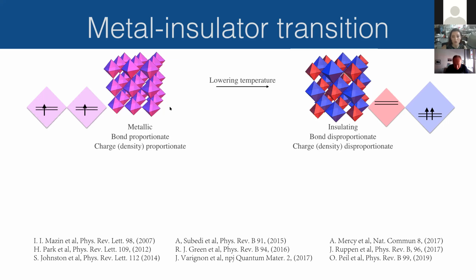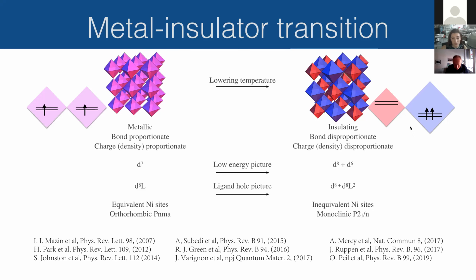Then, when you lower the temperature, you go through this metal insulator transition, and you get to the insulating state, which is a bit more interesting. So now you have alternating small and large octahedra, and going along with this, you have alternating empty EG orbitals, and now an EG orbital that has 2 electrons in a high spin configuration. So this is called bond disproportionate, because now there's 2 different sizes of nickel-oxygen bonds, depending on the octahedron you're in, and it's charge disproportionate. And you can describe this, like the low energy picture, which I have sketched here, or in the ligand hole picture, which is much more difficult to sketch. And in both cases, you have a charge disproportionation, either directly on the nickel or taking into account the nickel-oxygen complex. This is why I say charge density disproportionation, because it might be slightly more correct. So what you end up with is this insulating state that is highly disproportionate and has inequivalent nickels.